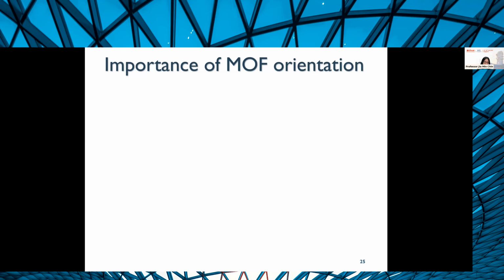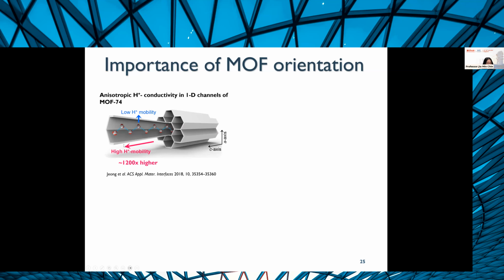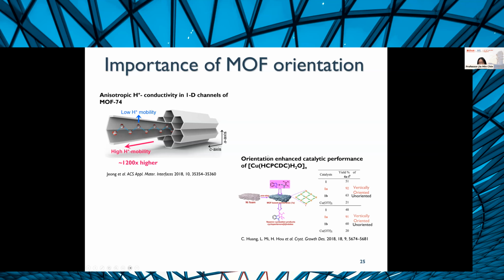Since structure is intrinsically tied to functionality, when you have an anisotropic MOF, its function and performance is very much tied to which crystallographic direction you're looking at. Take the example of MOF-74. MOF-74 has these one-dimensional channels. You could imagine that these channels will have completely different mass transport than when you look perpendicular to the channels. It was found that the mobility of the protons is 1,200 times higher along these 1D channels.